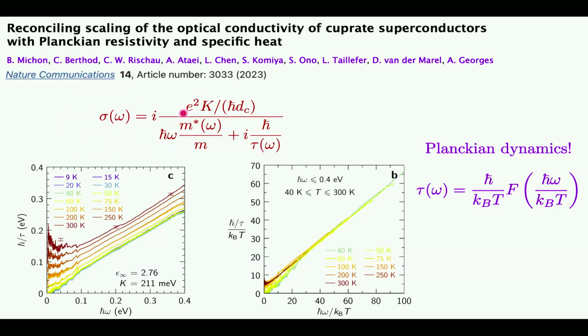Now, the Drude formula is exactly this formula here, where this mass, m star of omega, and tau of omega are constants. But when you do this for the cuprates, you find they're far from constants. And in particular, 1 over tau of omega is in fact a linear function of frequency over a wide range of frequencies. And when you scale the vertical axis by temperature, it also is a linear function of temperature. So in fact, you can summarize all of this data in this very beautiful formula that the frequency-dependent scattering time is given by exactly the Planckian time where the Boltzmann theory must fail.